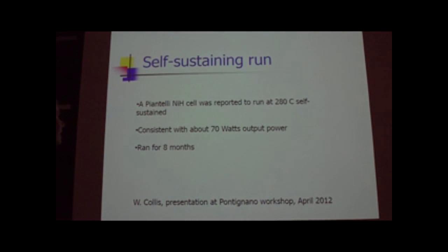Before going there, he remarked that at the Pontignano workshop, Bill Collis got up and spoke for Piantelli and reported observation of a nickel hydrogen cell to run in self-sustained operation at 280 C, consistent with about 70 watts of output power, and ran for 8 months. On the internet, I was looking around last night, apparently at the Atom Unexplored meeting, Ciampoli talked about 200 watts for 55 days, if I got my numbers correct. So this is not a unique report from the Piantelli group.